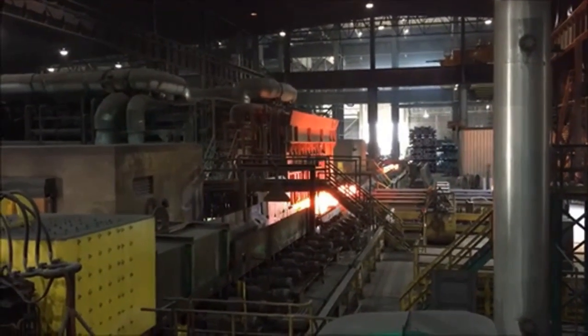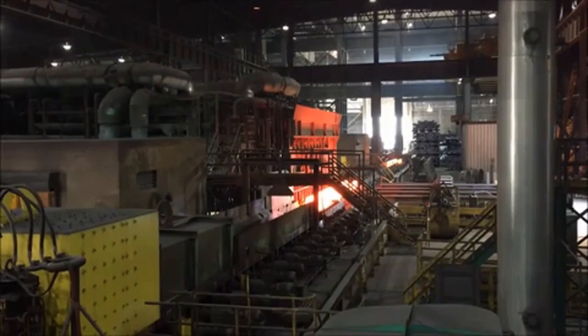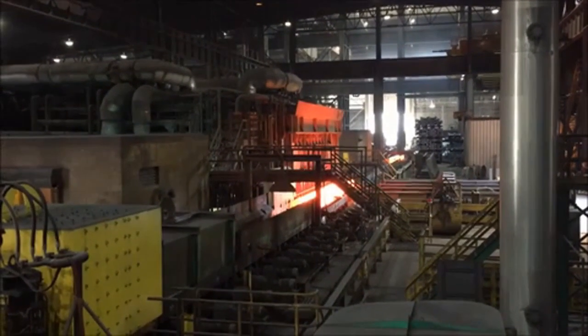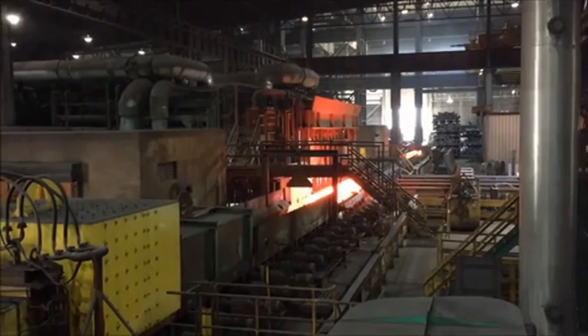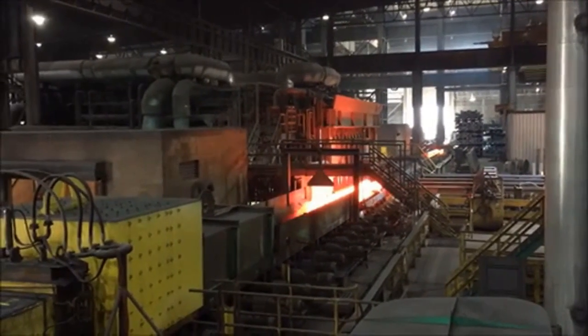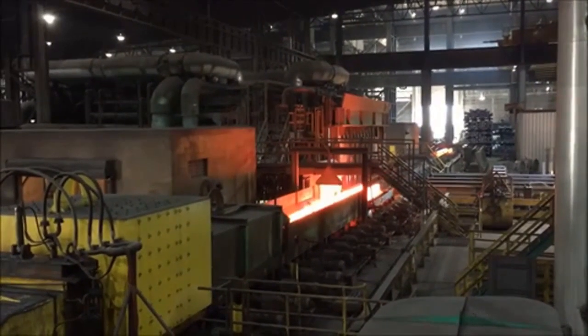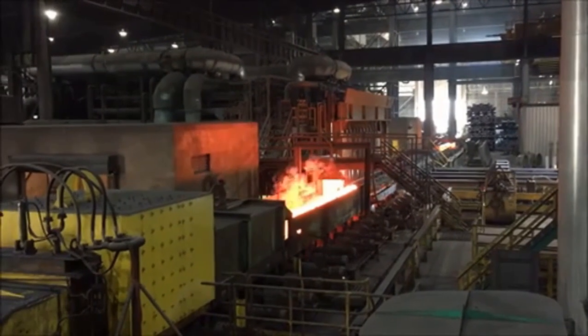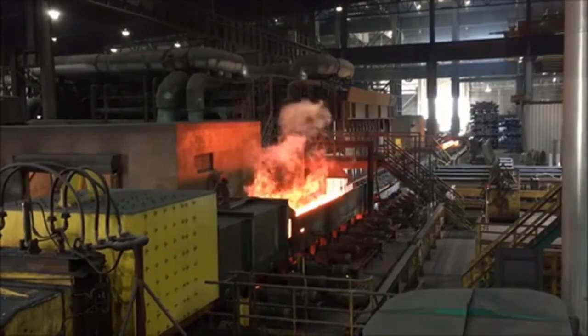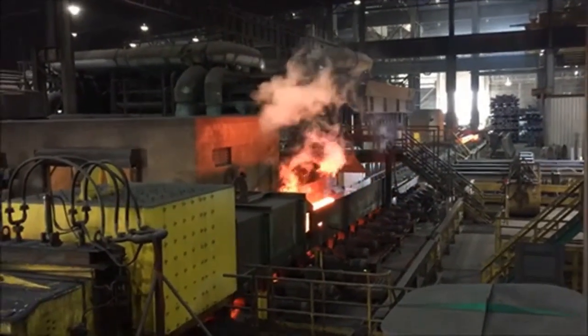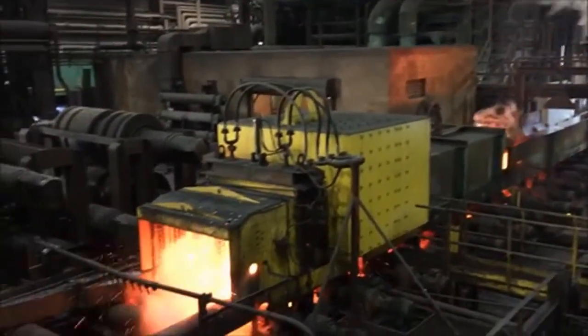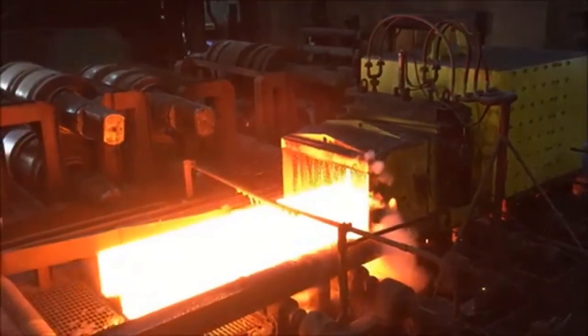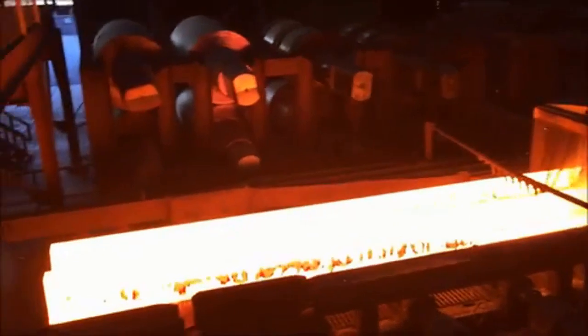If you're in a weld shop, for example, you have some slag, those oxides from that weld building up when we're done, or even with a heating torch, you have oxides build up from those temperature reactions. That's hard on the surface quality, and it can also damage the rolls. So we like to minimize that scale when it goes into the process. So again, this is a beam blank going through the descaler.